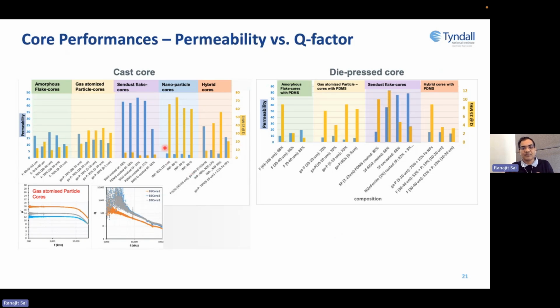This is a too busy slide. I'm not going there. I just wanted to show that in some cases, if you get high permeability, these blue color towers, then you are getting low Q factor. But if you are getting high Q factor, your permeability is low. So this is the kind of trade-off one has to play with, and then optimize the process.